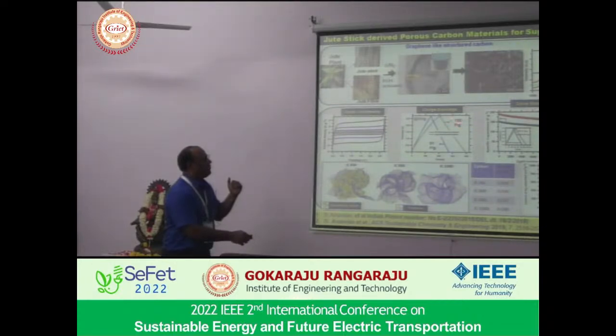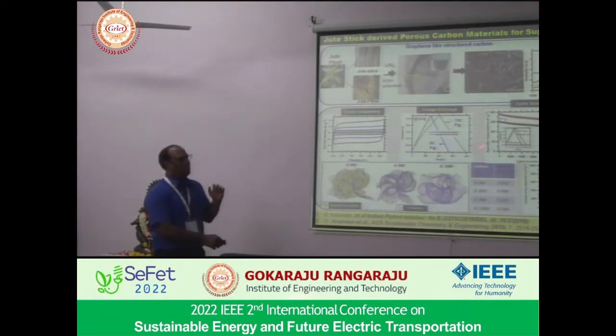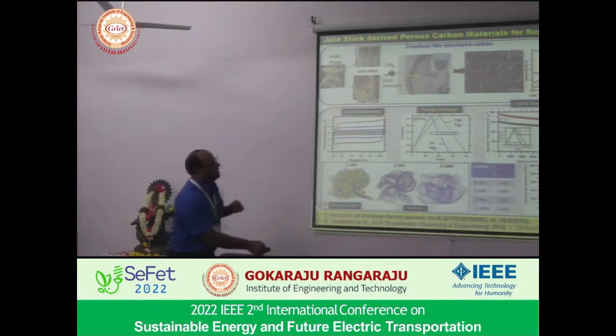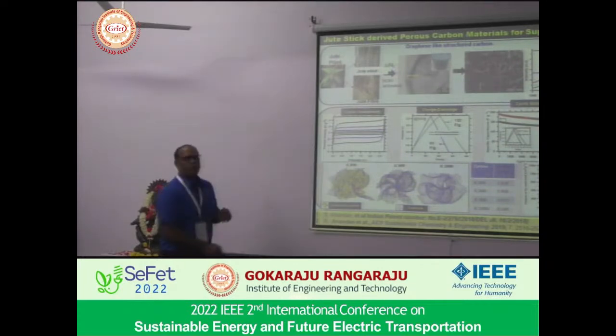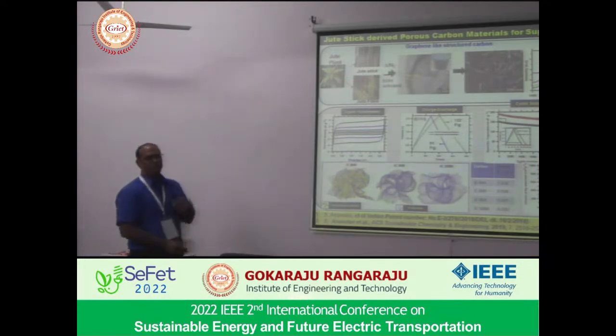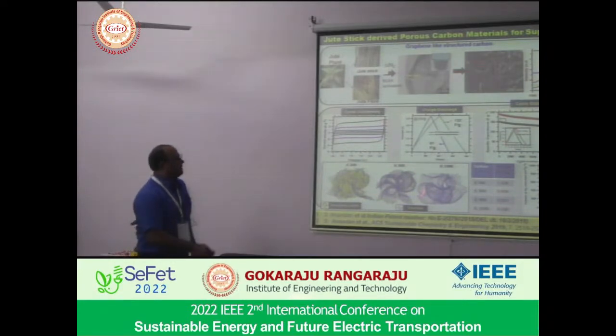Our material could deliver 132 farad per gram, whereas the commercial material can deliver 91 farad per gram, and for more than 10,000 cycles it can retain more than 80% retention. That is the advantage of supercapacitor, whereas a lithium ion battery hardly lasts a few thousand cycles. So this work also we have filed a patent and we have published the paper.